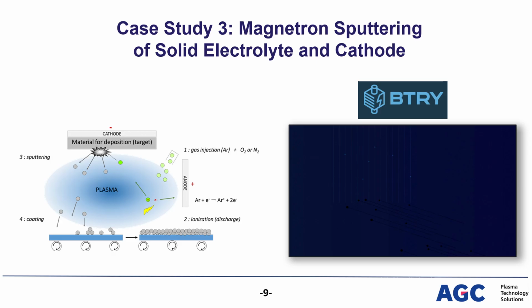The positively charged gas ions are attracted towards the cathode and will strike the target material at an extremely high velocity. The bombarding ions eject atoms from the target surface, which move across the vacuum vessel and are deposited as a thin film of material. The process can be performed in an inert atmosphere, like argon to deposit metal films, or in oxygen to deposit oxides, or in nitrogen to deposit nitrides. By putting several cathodes one next to each other, a complex coating stack can be deposited in one single pass through the machine.